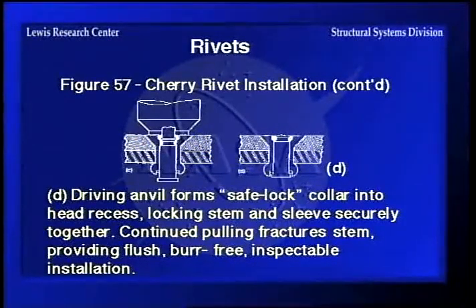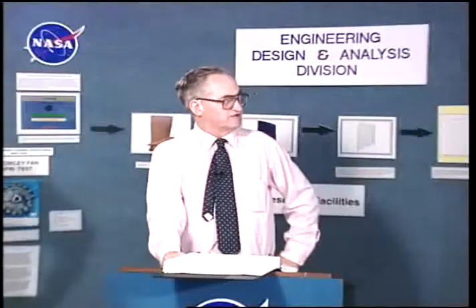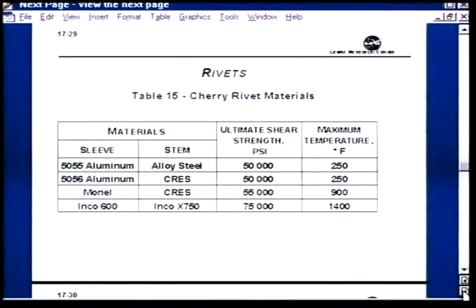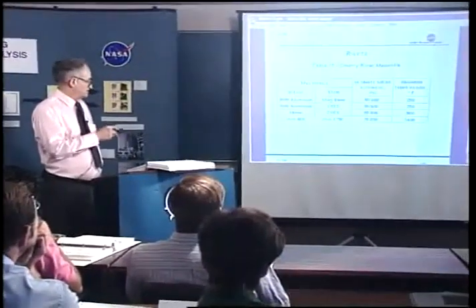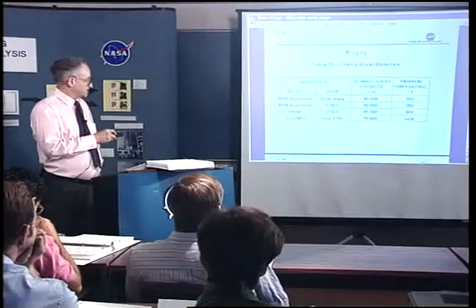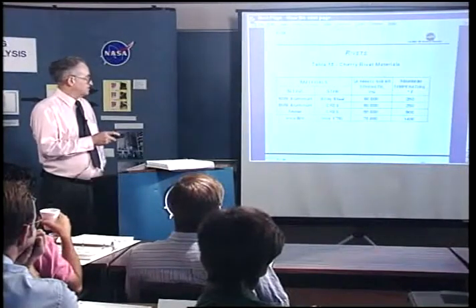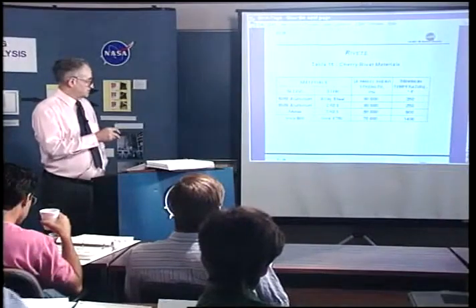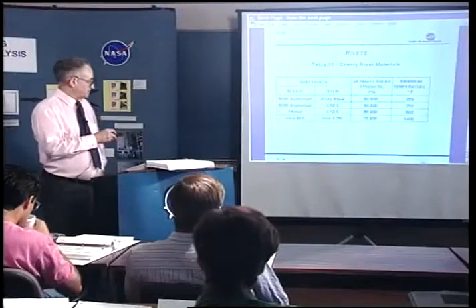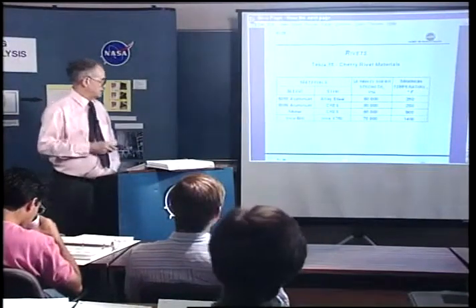Now here is a table of Cherry rivet materials, and notice that the stem and the sleeve are different materials, because the stem has to be strong to pull through and deform the sleeve. The sleeve has to be ductile enough to form without cracking. So the strength of the rivet is a combination of those two materials. So like here, if you have the 5055 aluminum with alloy steel, Monel with stainless steel, and here's an Inconel 600 with an Inconel X750 pull stem on it. And look, you can kick the temperature way up by going to the temperature resistant nickel stainlesses.